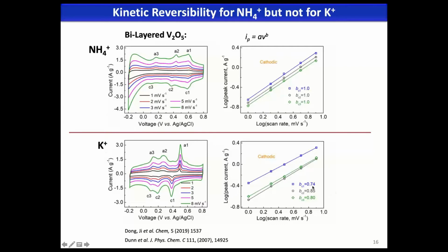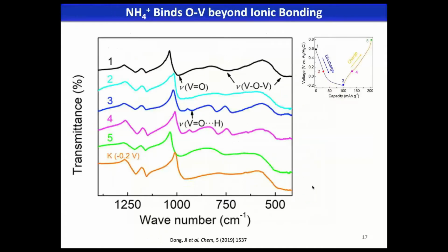And for potassium, it's doing pretty well, 0.7, 0.8. It's not bad. We can still call this quasi-capacitive, but it's way slower than ammonium. Now, in terms of the chemical bonding, we did a simple FTIR measurement, and you can see this is the initial V2O5 and the VO vibrations, and we look at these 3 peaks.